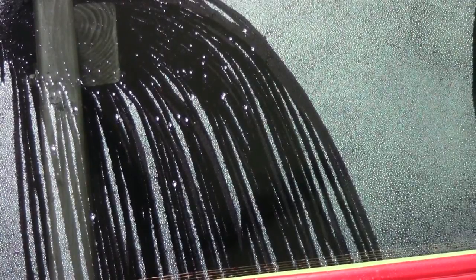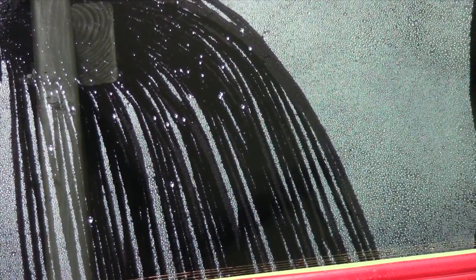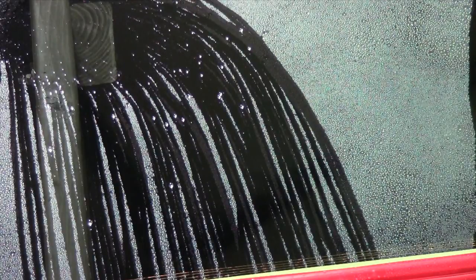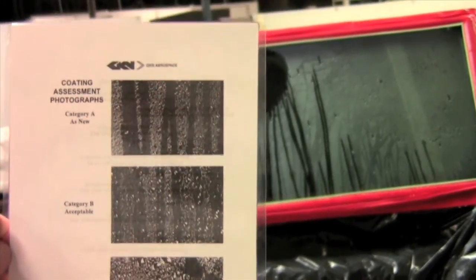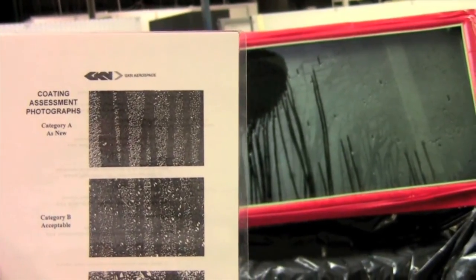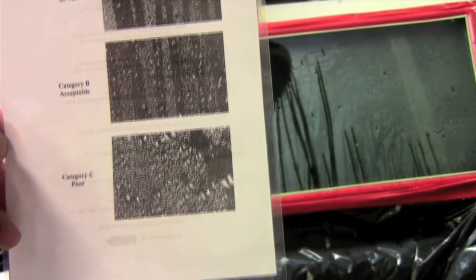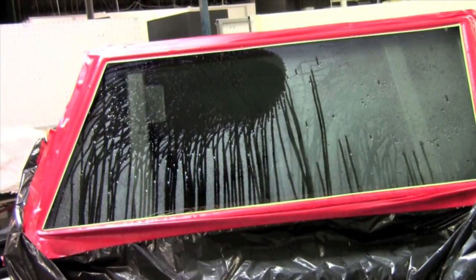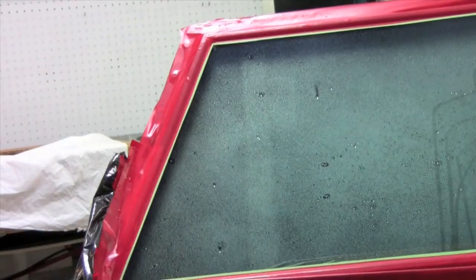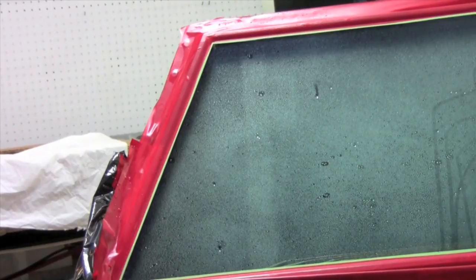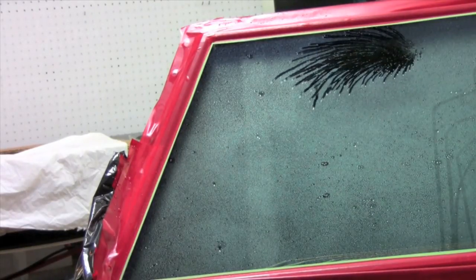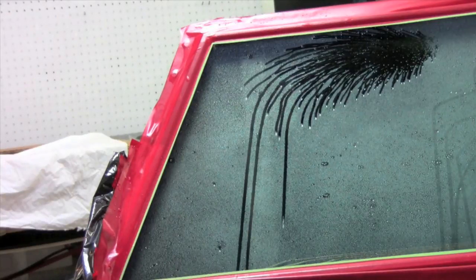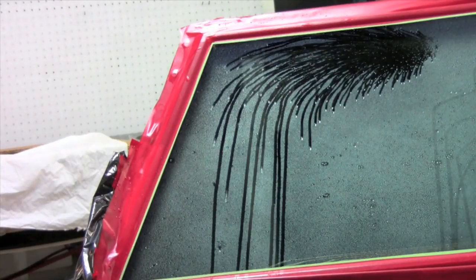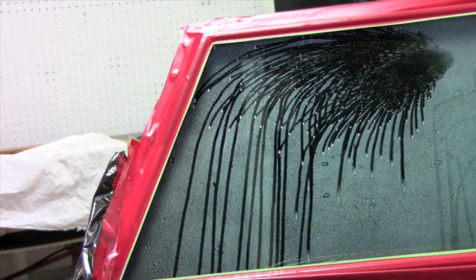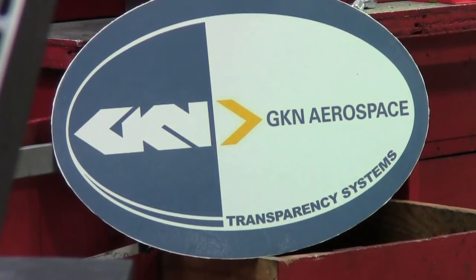Coating B, acceptable performance. The sprayed water will remain beaded up, but the droplet size will be evidently larger than in coating A. However, the tracks will not be completely void of droplets. Some droplets will remain in the path of the track and are usually elliptical in shape. This coating will probably need replenishing in the next maintenance interval. Coating C, poor performance. The sprayed water will form large areas of unbroken thin films. Tracks formed from moving water are liable to be populated with large droplets and possibly continuous streaks of water. The Surfex 100 coating needs to be reapplied.